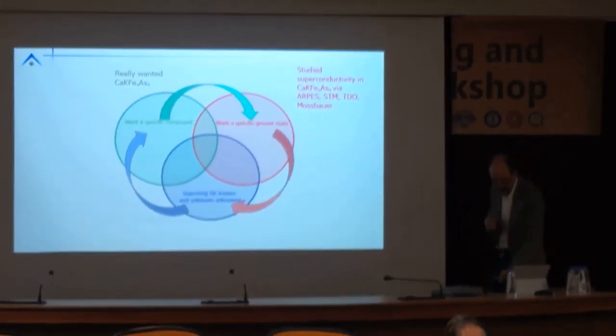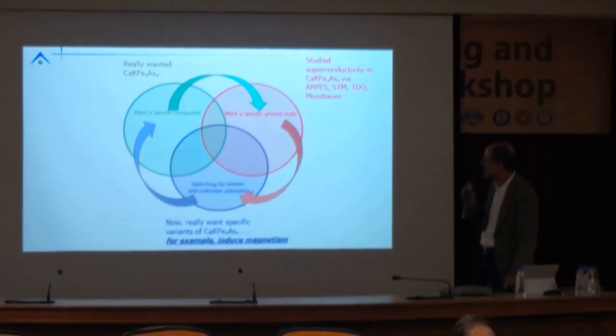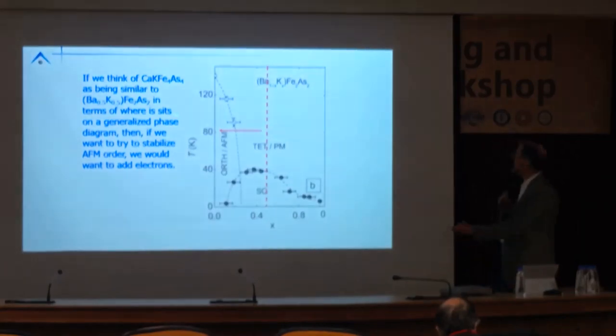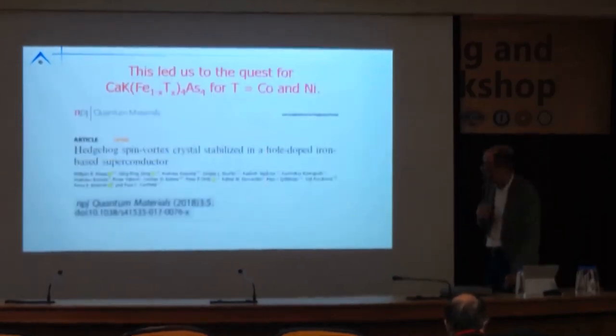and so on. And then we wanted to ask a question. This is a material that has a superconducting transition at 35 Kelvin and no magnetic or structural phase transition. And the reason we ask that is if we look at the barium potassium phase diagram, which electronically is similar to what we're looking at here, the 1144 is the same as a 50-50 barium potassium mix. That's near maximum Tc. And if we wanted to have some sort of structural or magnetic transition, we'd want to add electrons. So this led to a desire of adding cobalt and nickel and going from a quaternary to a quinary growth.